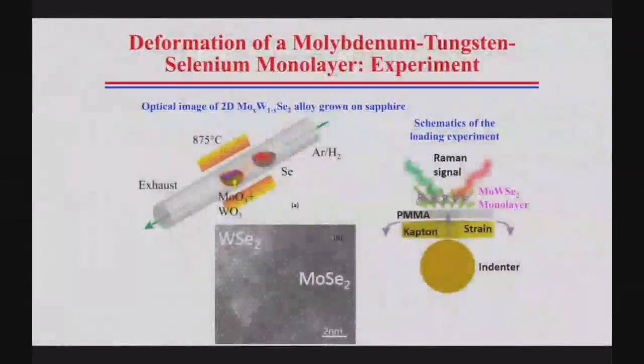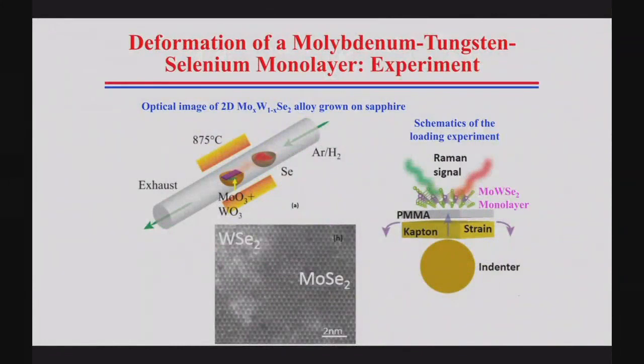And then a second material. So this material, now instead of having just molybdenum and selenium, there is a third element, which is tungsten. Our collaborator, Ajay at Rice University, synthesized this material. The way it is done is you have a substrate, and the substrate is sapphire, which is aluminum oxide. On that, they deposited this material using a method called chemical vapor deposition.